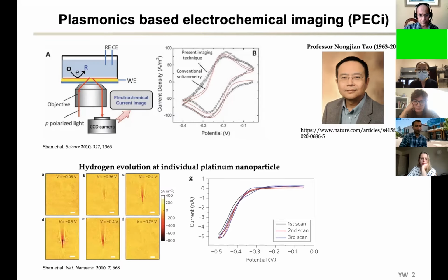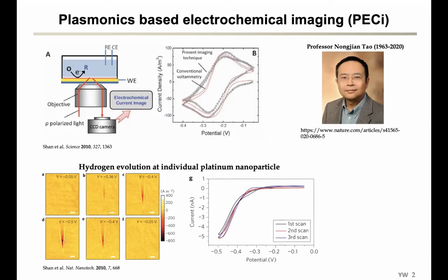Later on, they applied this technique to study hydrogen evolution at individual platinum nanoparticles. The example we're showing here is from a nanoparticle that is about 8 nanometers in size, so it has very good sensitivity. And just to add a small note on the shape of the signal: when you're using SPR or plasmonic imaging to look at individual particles, you will normally see a very long tail behind the particle.